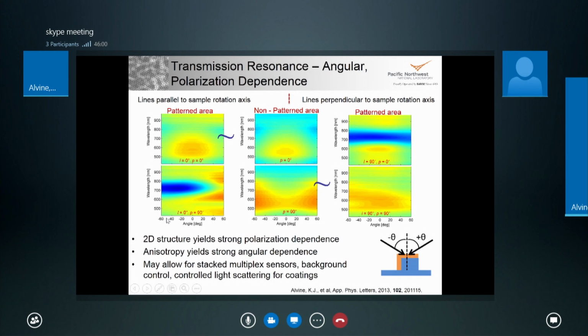The reason why the lower left one is highly angular dependent - the x-axis is the angle of incidence as we rotate the sample about the normal incidence beam - is because you are changing the cross-sectional projection of the electric field on the shells. In the upper right figure, the polarization is still perpendicular to the lines, but now the projection isn't changing because of the way you're rotating the film. And in cases where you don't have perpendicular crossing of the polarization and the lines, you get something that's not plasmonic, and you don't get a resonance at all.